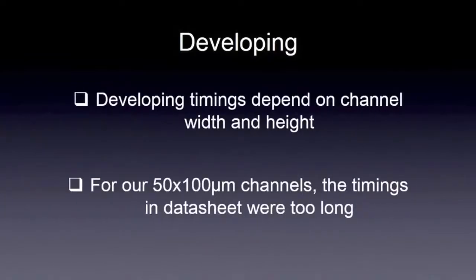We found that for our designs of 50 by 100 microns, the timings in the datasheet resulted in significantly overdeveloped channels.